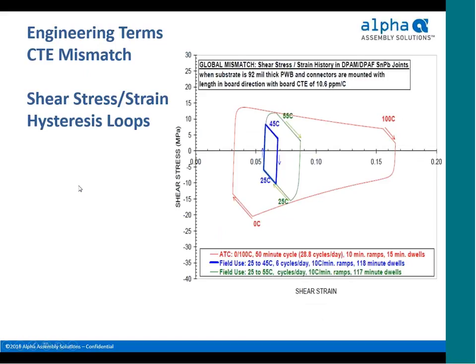Here's an interesting little graph that takes a little bit to see what it's trying to visualize. What this graph is trying to show is the effect of the stress that's applied to a test vehicle depending on differences in the levels of temperature at different set points. For example, the blue box here shows you 25 to 45 degrees C, 6 cycles a day, 10 C per minute ramps, and there's a relatively narrow range of stresses that's applied to the assembly. And when you just change from 25 to 55 degrees C, so a 10 degree change in your upper temperature, you can see it's a pretty big expansion of the square there that represents the stresses that are applied during that kind of testing.